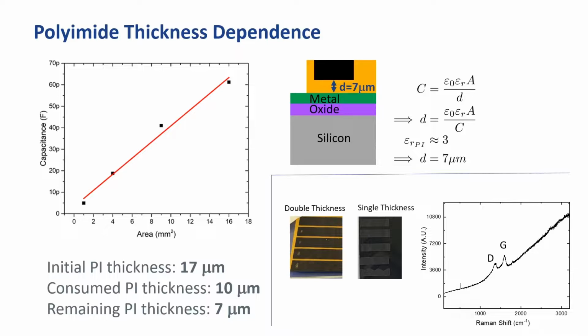We ascribe this thickness dependence in part to the photothermal nature of the laser-induced graphene formation, whereby the thermally insulating polyimide is rapidly heated by a laser source, and a short-lived localized plasma is formed, resulting in the evolution of small molecules and the healing of the carbon backbone towards a graphene-like material. If the polyimide is too thin, then the heat can escape to the support, preventing efficient conversion to a graphene-like material. So, beyond being a convenient method of self-insulating the top conductive layer from the back contact, it is also a mechanistic requirement to produce high-quality material.